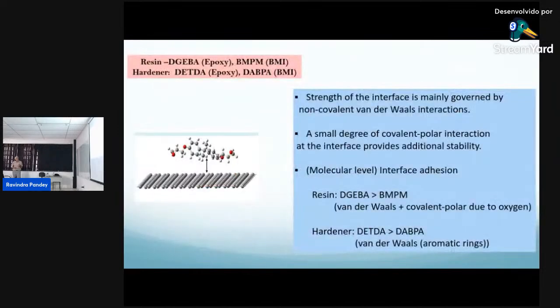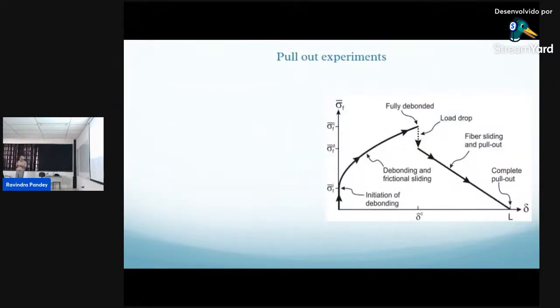So what kind of experiment do they do? Simply they have experiments to look at the strength of the material by pull-out experiment. So you have this polymer matrix, fiber, and simply pull it out. Very easy experiment. So what they're doing here, this is strain, they are applying. This is the stress, and this is the initial stage of debonding, and they're pulling it out, and at one point, it breaks. So that's what we have, the debonded, and then it goes down. It's completely collapsed. So the key thing is, what they would like to know, what is this critical point that determines if a material is tough or not.